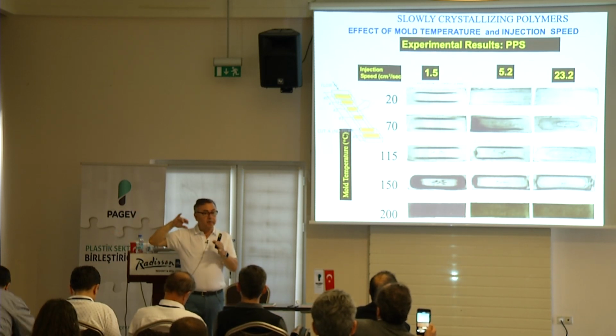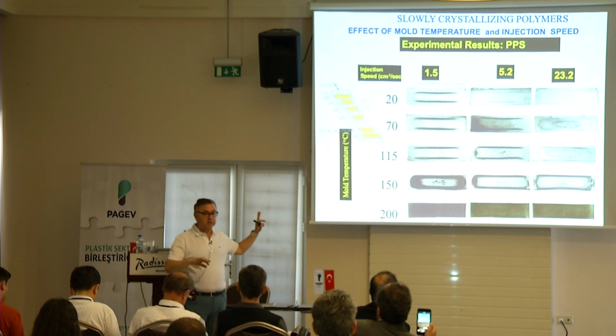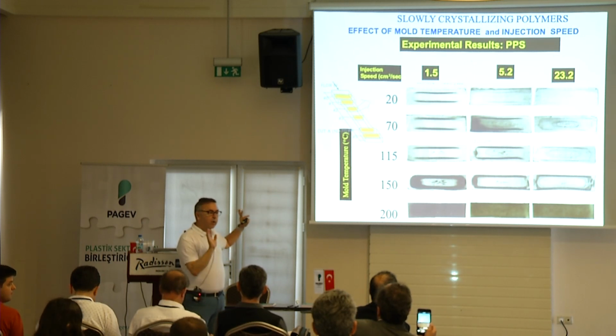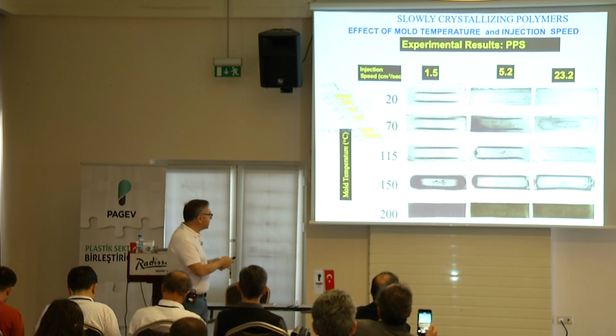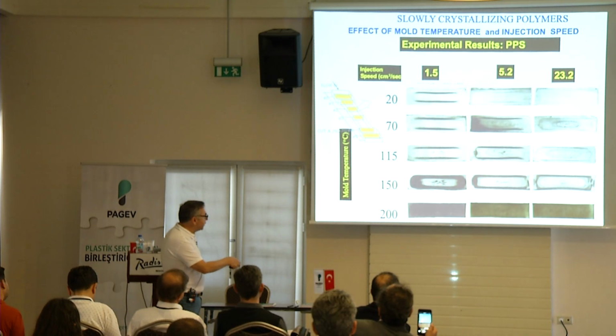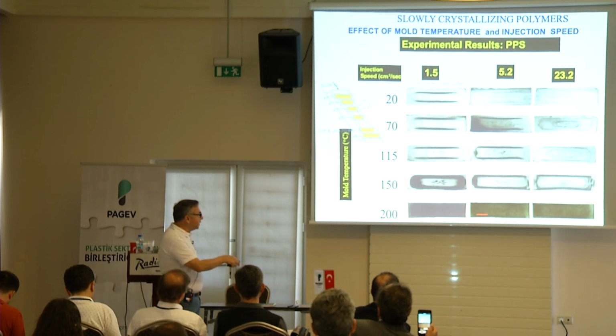I'm going to bring back both of them together, but before we do that, I want you to see pure oriented, not necessarily shear, but oriented crystallization. This is oriented crystallization up to about this point. Beyond that, it gets complicated because thermal crystallization kicks in, because you are above the glass transition temperature, so things are happening even if you're not doing any flow.